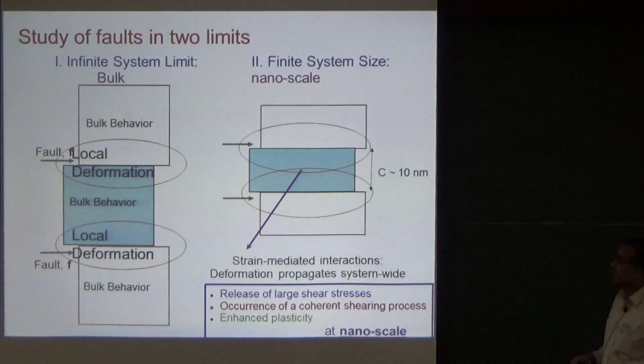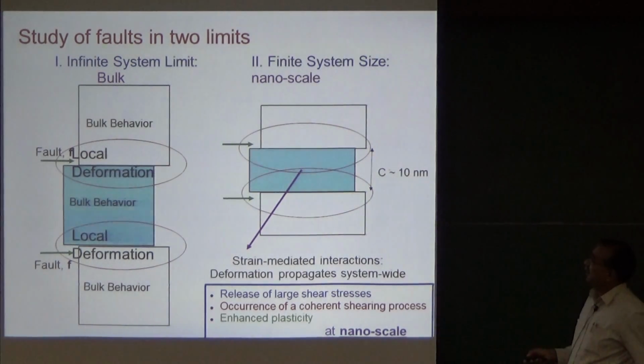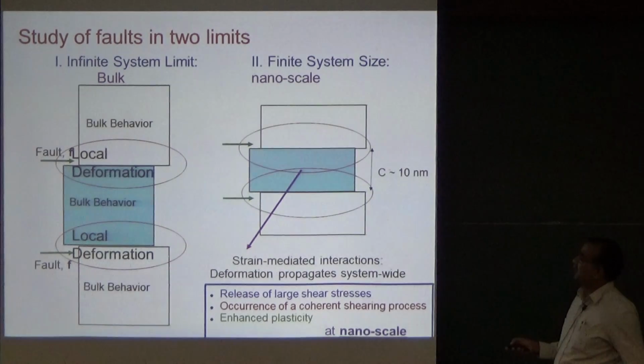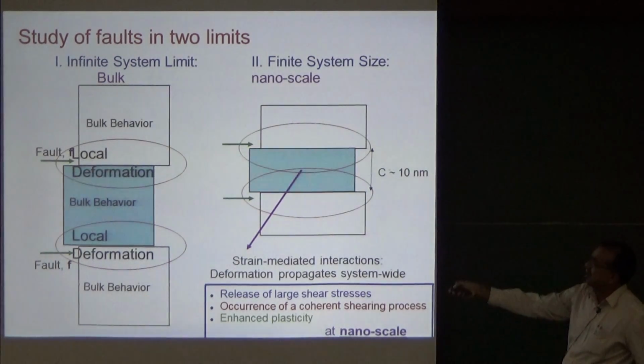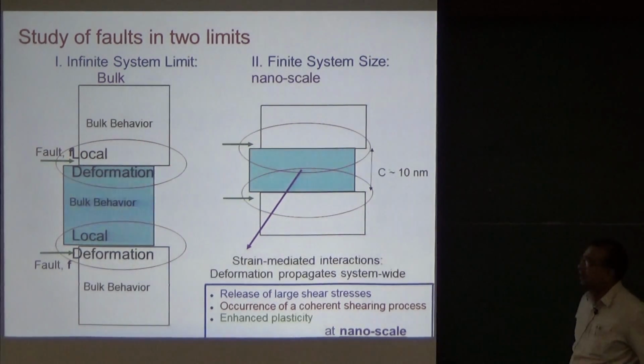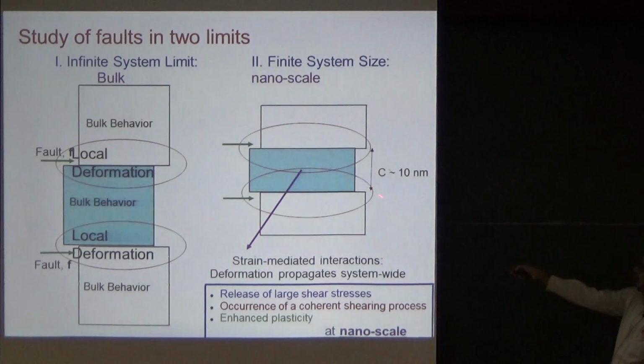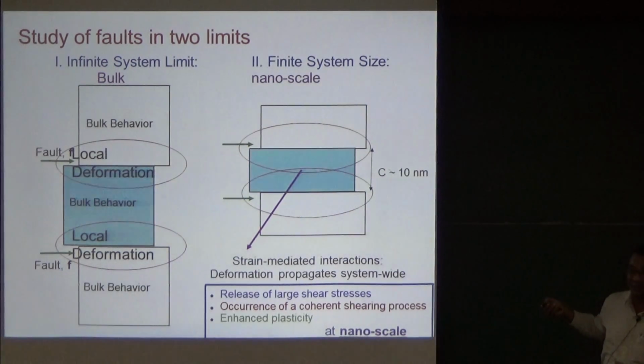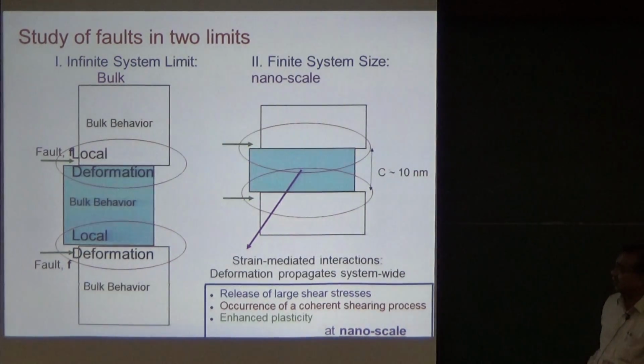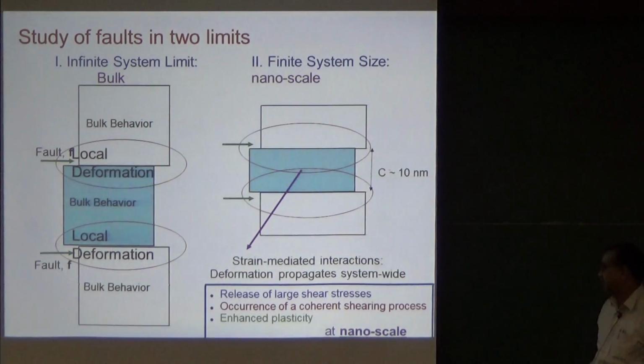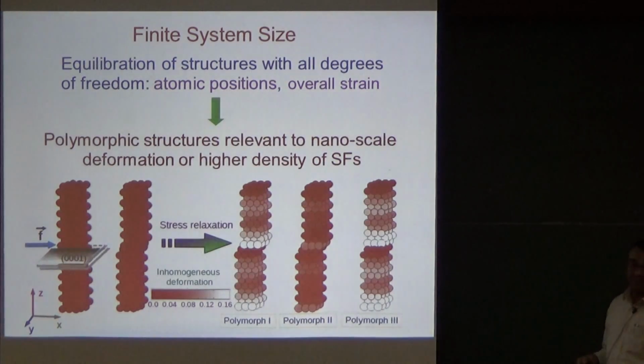Again, for lack of time, I'll be going quickly through this. So what we did is basically study these two phenomena in these two limits. One is called bulk HCP metals, where we use stacking fault and dislocation systems which are far away from each other. And in the nanoscale, what happens is you can have two dislocations which are pretty close to each other, and they can have fairly strong interactions with each other. Okay, and that's about 10 nanometers that we looked at. So you have strain-mediated interactions between neighboring dislocation systems, and that can release large stresses, which we show by the occurrence of a coherent shearing process. So that's our main finding.